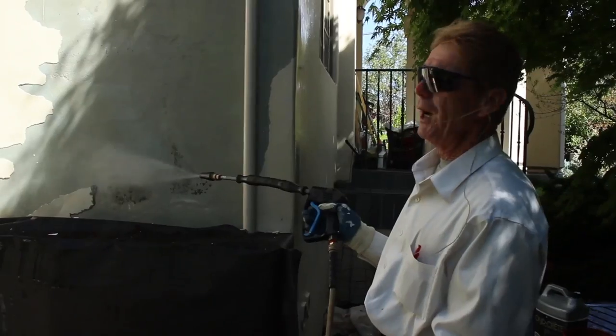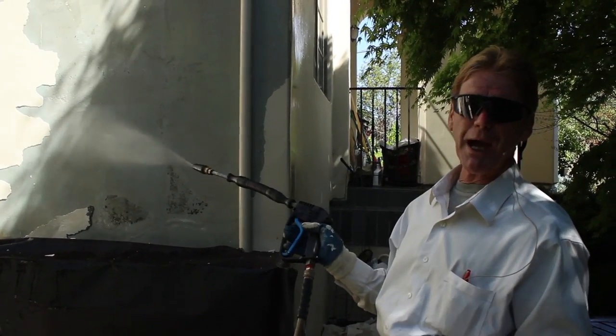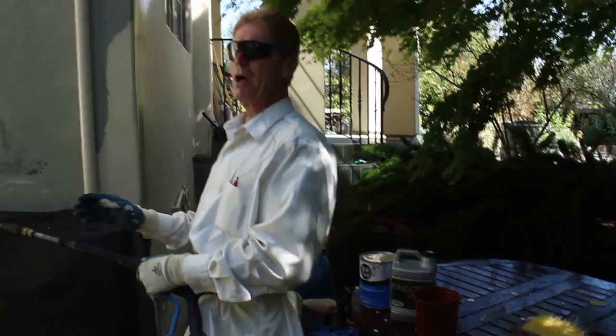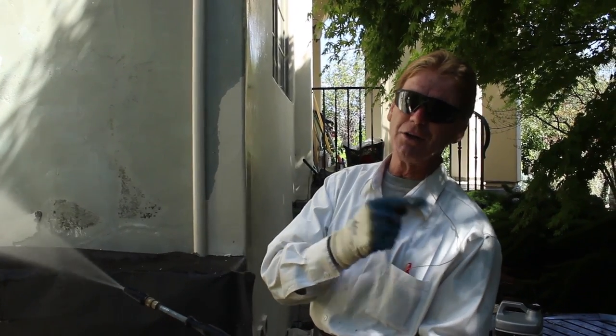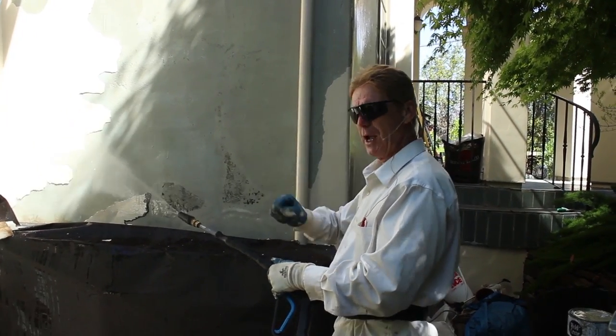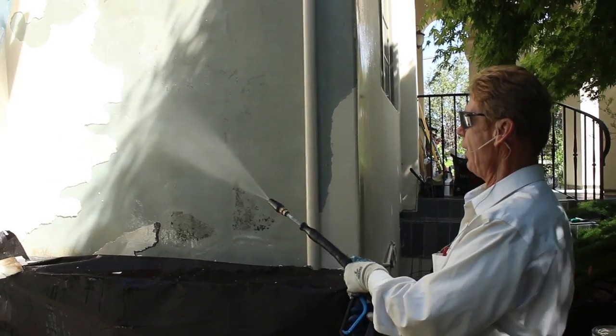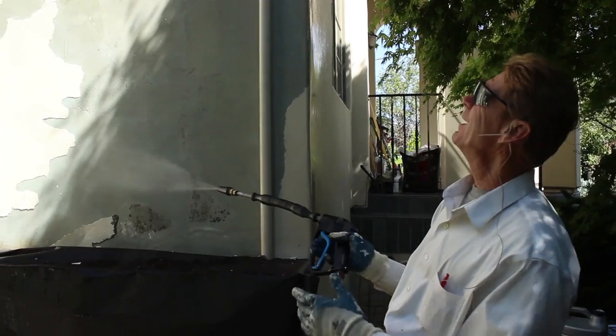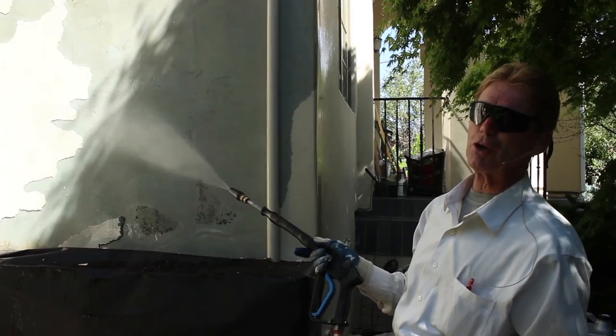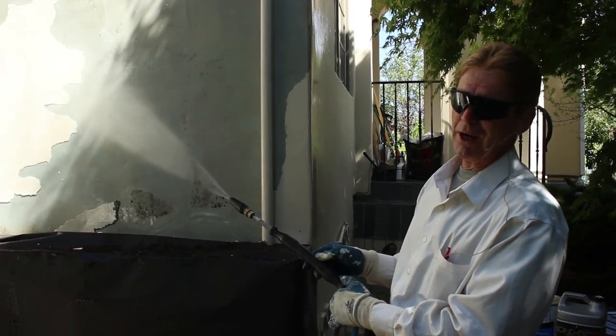This is a result of guys not applying the proper mechanical bond, which can be a bonding agent. A bonding agent will work, but when you're doing a color coat you don't really need a bonding agent. The mechanical bond requires you to have the wall wet and your finish wet when you apply it - that's how it adheres. The owner also asked how it could look like sags, and I said they used an elastomeric paint - usually all acrylic - and that won't allow water to penetrate.